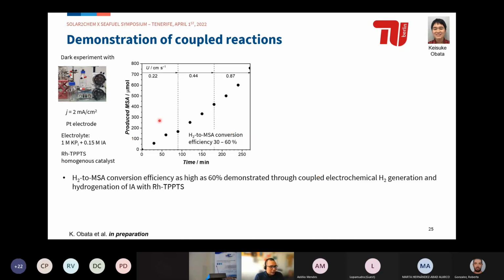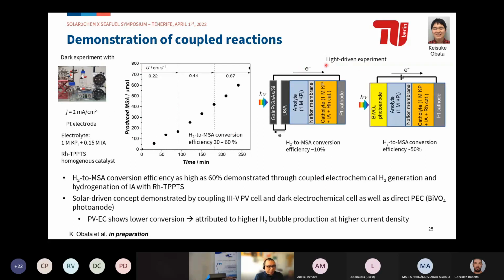Since we could do this in the dark, we could also do this under solar-driven experiments. We used photoelectrochemical configurations as well as photovoltaic-driven electrochemical configurations. Under photoelectrochemical configurations, we got a conversion efficiency of about 50%, similarly high as under dark conditions. But when we shift to photovoltaic electrochemical configurations, we have lower conversion of only about 10%.